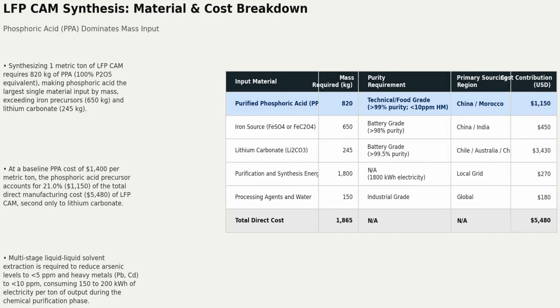Chemical synthesis of lithium-iron-phosphate cathode material reveals why this intermediate chemical is so critical. Producing 1 metric ton of cathode active material requires 820 kilograms of purified phosphoric acid. This makes phosphoric acid the largest single input by mass, exceeding both iron precursors and lithium carbonate. At baseline market rates, this single precursor accounts for 21% of the total direct manufacturing cost.